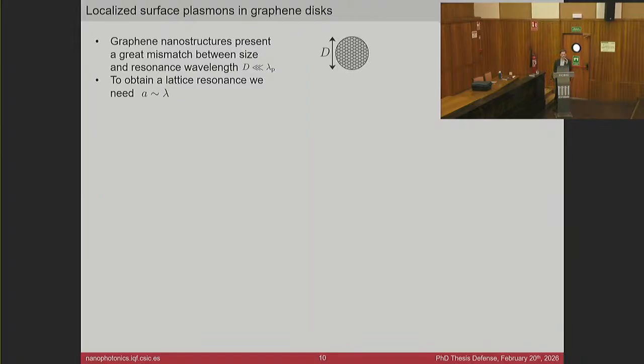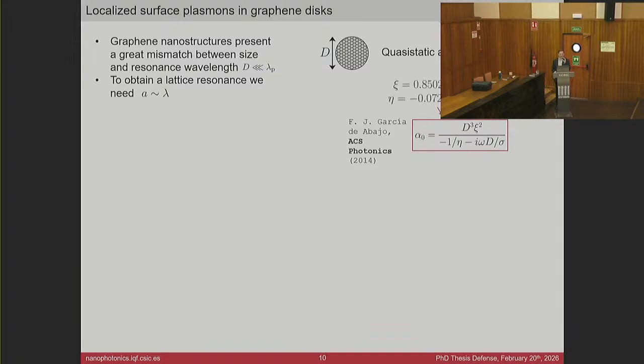We are going to take advantage of this mismatch between size and wavelength to model graphene in a quasi-static approximation, in which its response can be described by an electrostatic potential, as is done in electrostatics. And in this way, we can obtain this really general polarizability that depends on some parameters that only depend on the geometry of the nanostructure, but not on the actual size. And then we introduce the material properties through the conductivity model. Now, with this polarizability, we can derive the ratio between the diameter, the size of the nanostructure, and the resonance wavelength. And we can see that this increases with diameter and Fermi energy. So what we have to do is work with high diameter and Fermi energy. For example, we are going to use a Fermi energy of 1 electron volt and a diameter of 10 microns.